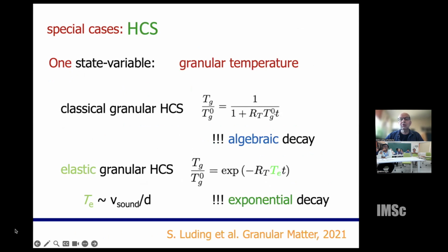Take the granular temperature, it's decaying algebraically in a granular gas. In the gas or fluid state, the decay is algebraic, 1 over time for long times. In the elastic system, above jamming, it's exponential. So the theory makes a difference between the fluid state and the solid state. You see algebraic versus exponential decay. And this was something of a surprise for me because the exponential I didn't know. I saw it in the theory first, and then I looked at my simulations again, and actually the simulations confirm what I observe, algebraic versus exponential in a fluid or in a solid.